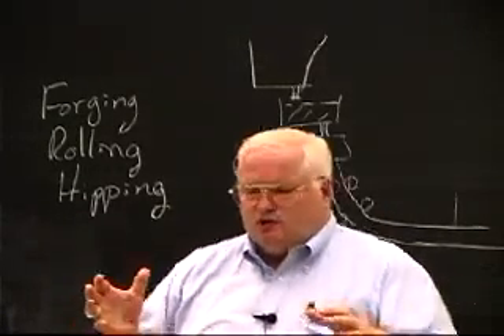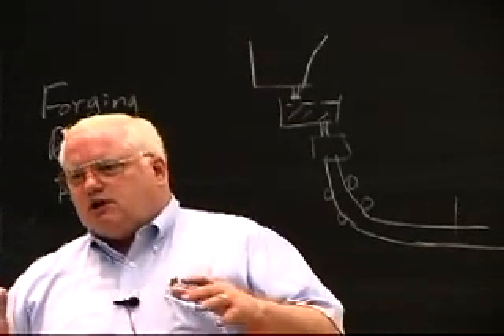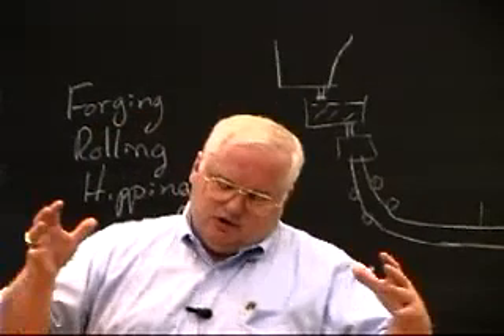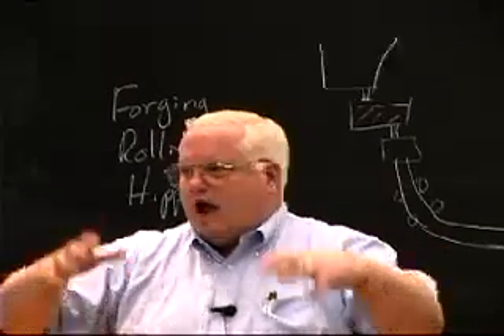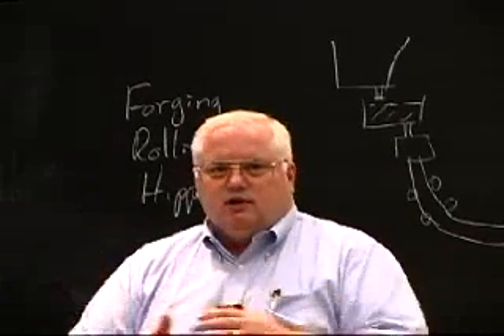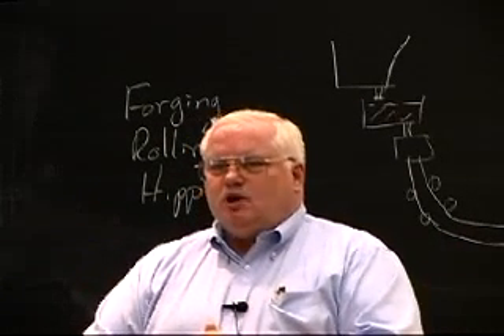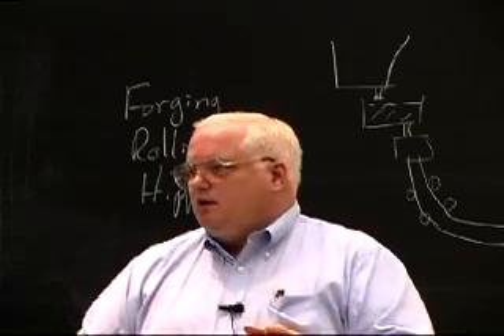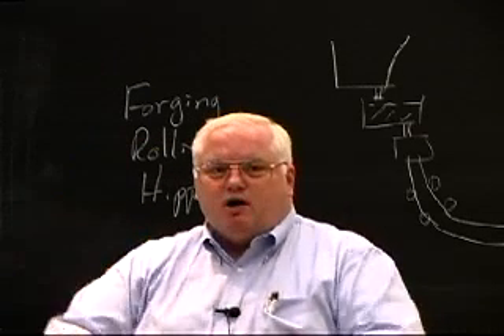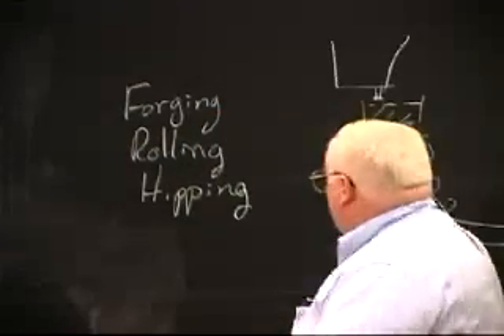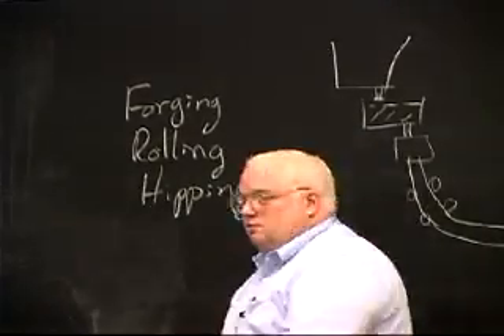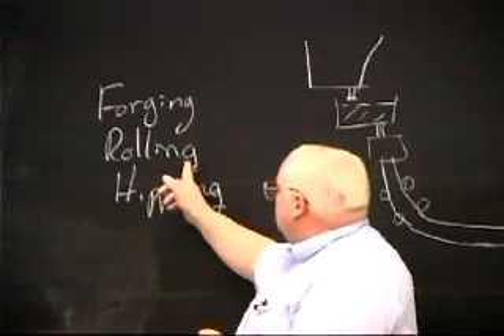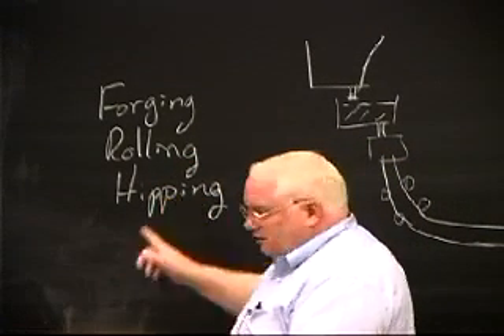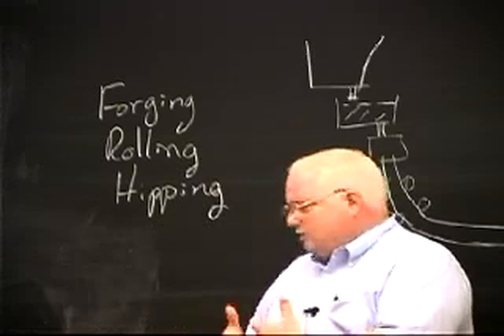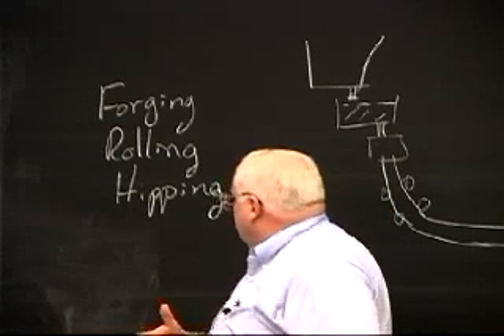Capped steel, you could control the porosity size a little better if you put this kind of 2,000-pound cap on top of this boiling steel. The problem is you didn't want to be too close if they put the cap on too early, because sometimes it'd blow the hot cap off and you'd have molten steel fly all over for about 20 yards around. And people used to get killed in the steel mill when it happened if they were too close to it.